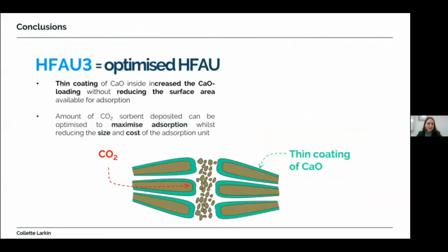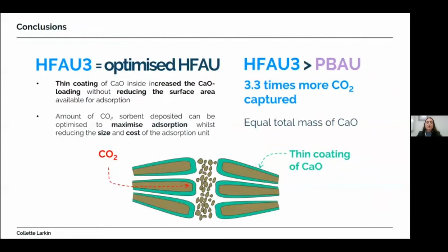Additionally, the optimized hollow fibre adsorption unit outperformed a packed bed adsorption unit despite the two units using an equal mass of calcium oxide. And the improved CO2 capture performance of the optimized hollow fibre adsorption unit 3 can be explained by the morphology of the hollow fibre adsorption unit achieving an intensified contact between the CO2 and the calcium oxide due to the minimized mass transfer resistances and narrow residence time distribution.